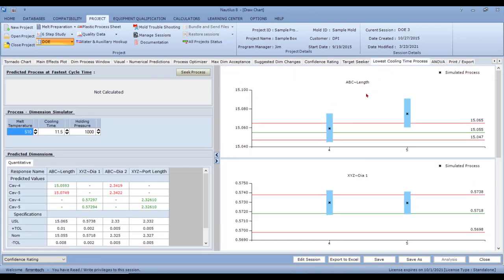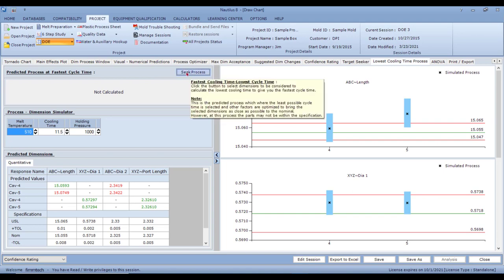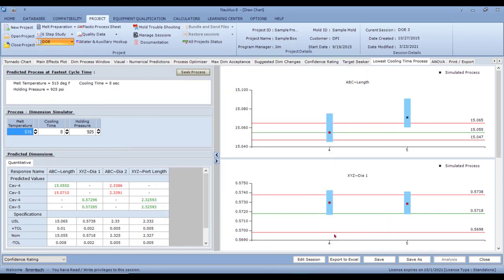The Lowest Cooling Time tab automatically tells you, for the dimensions and cavities you selected, what molding process achieves those dimensions at the lowest possible cooling time. Leave out cavity 5 and the out-of-spec dimensions, click OK, and it tells you the process is 515°F, eight seconds cooling, and 925 PSI holding pressure — giving you a process to make good parts in spec at the fastest cycle time.